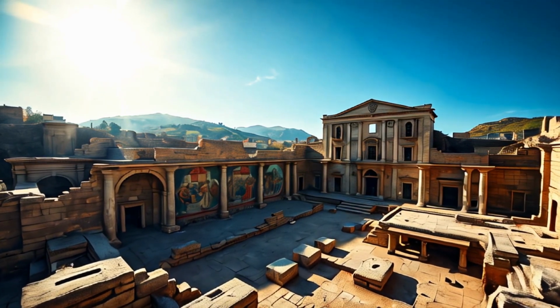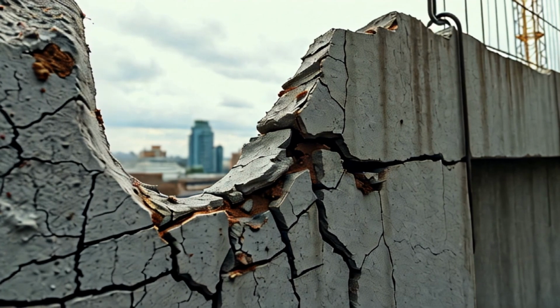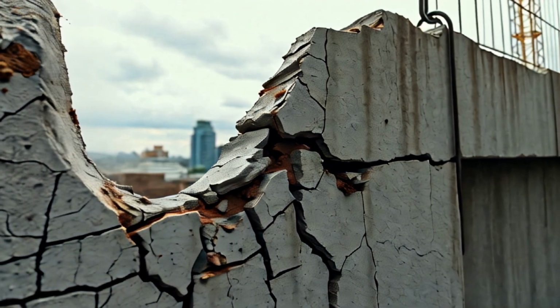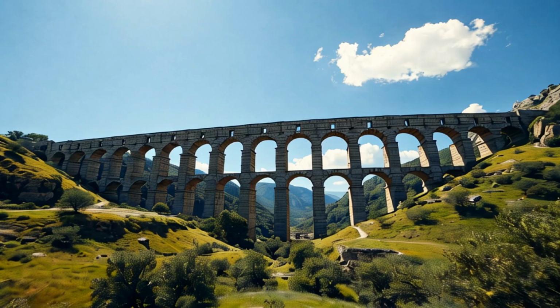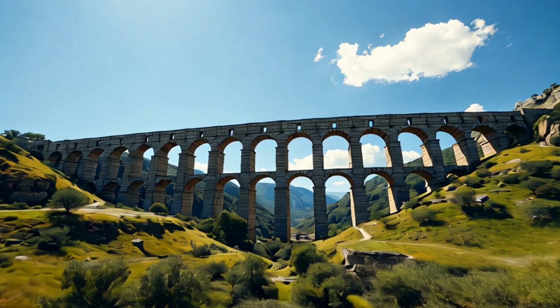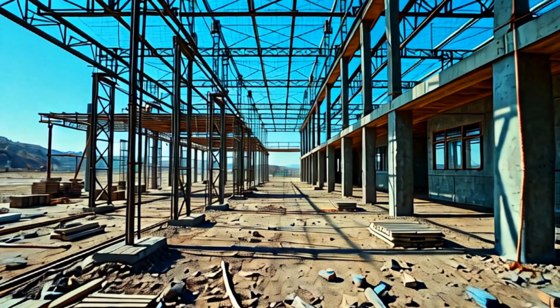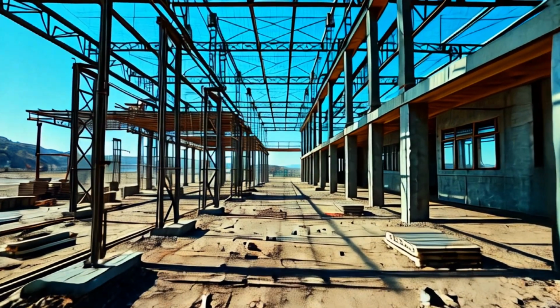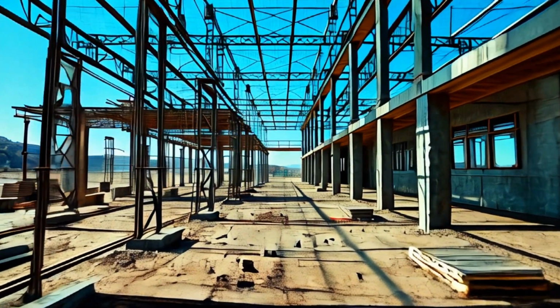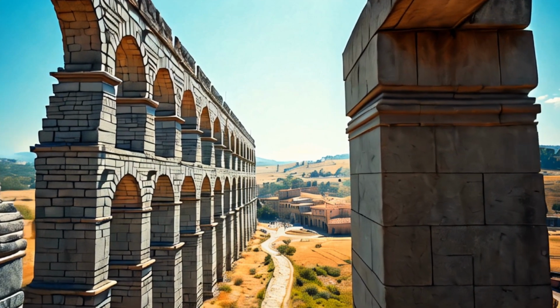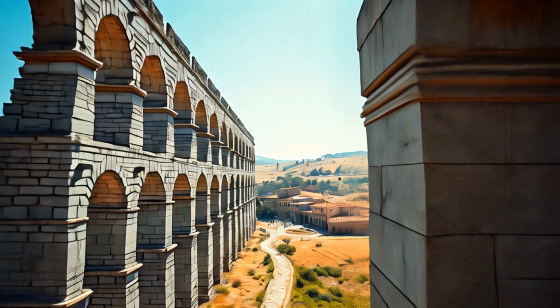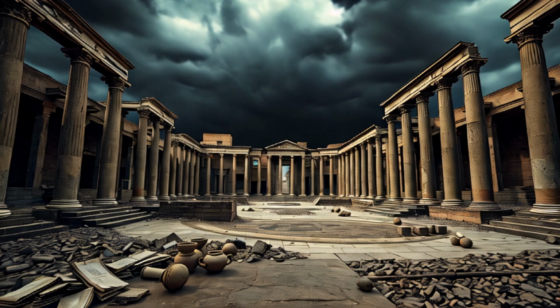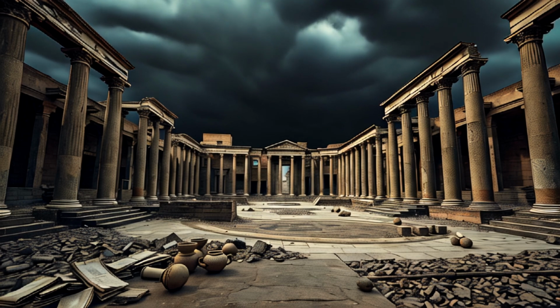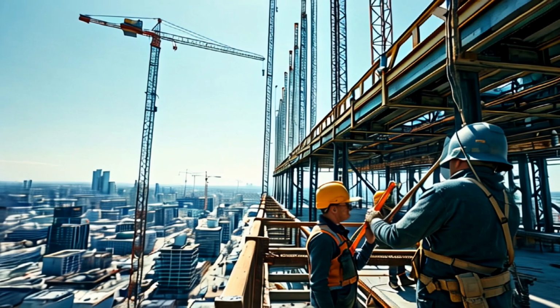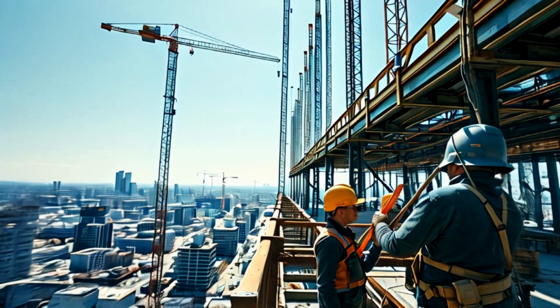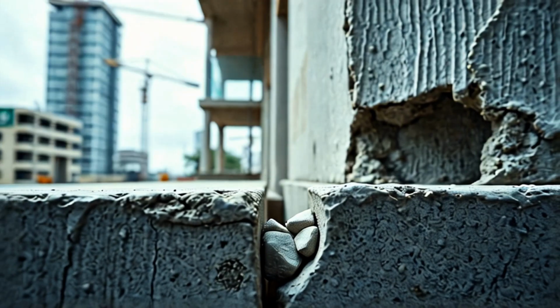4. Lack of cracking. The combination of volcanic ash and lime, along with the slow-setting nature of Roman concrete, resulted in a material that was much less prone to cracking. The material's inherent ability to resist cracking is one reason why Roman structures, like the Pantheon, remain intact after more than 2,000 years. Modern concrete, by contrast, tends to crack over time due to its faster setting nature, exposure to moisture, and the limitations of Portland cement, which can shrink and crack as it dries.